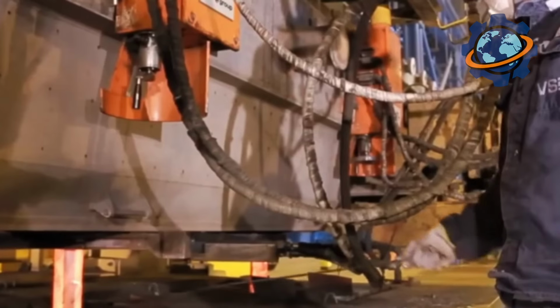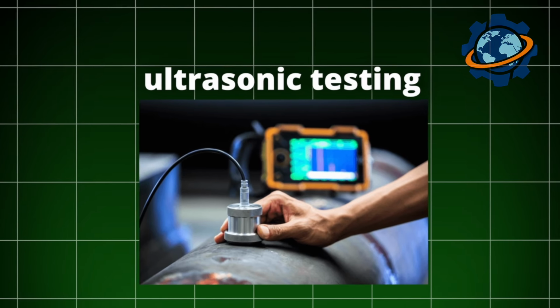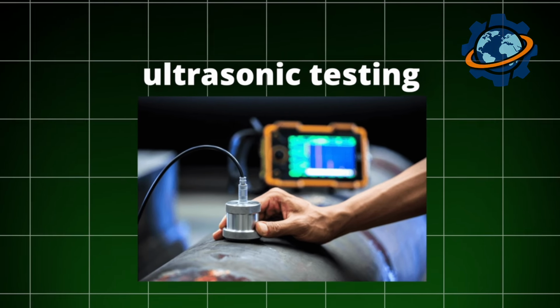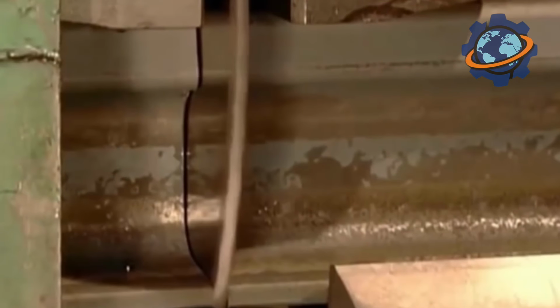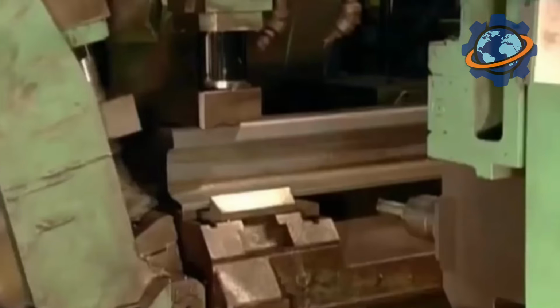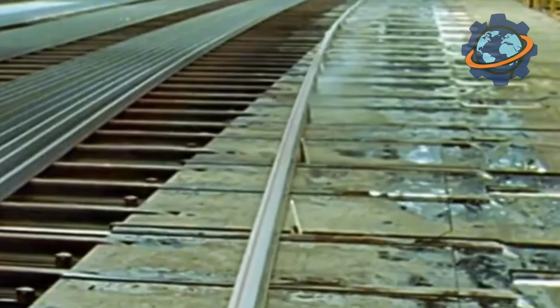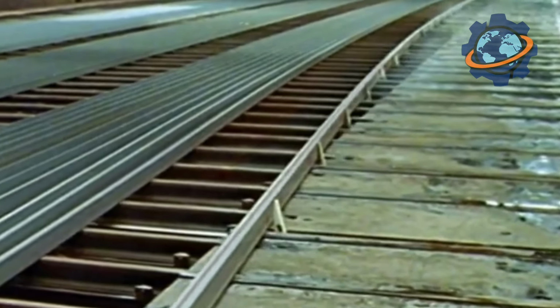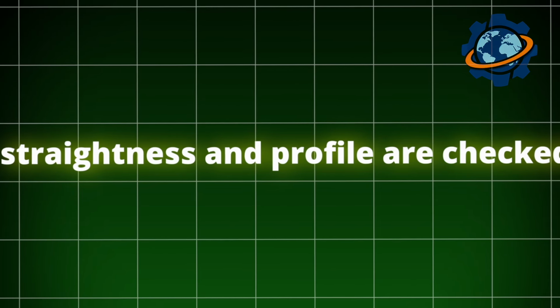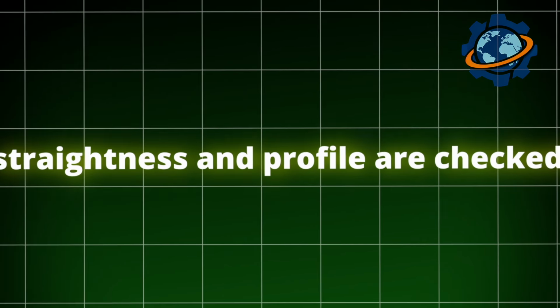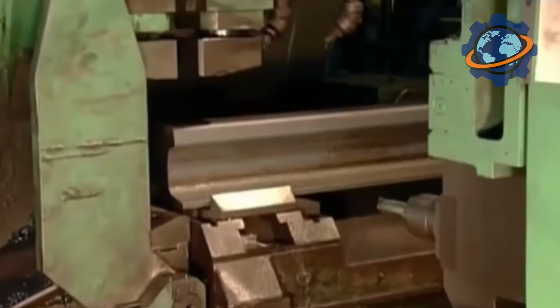In special labs, it's checked for strength, hardness, geometry, and internal defects. First up, ultrasonic testing. High-frequency waves are sent into the rail. If there's a microcrack or void inside, the signal bounces back and flags the problem. Then, hardness measurements along its entire length to make sure the heat treatment was uniform. At the same time, its straightness and profile are checked. Laser sensors scan every inch, detecting even tiny warps that could cause vibration or wear.